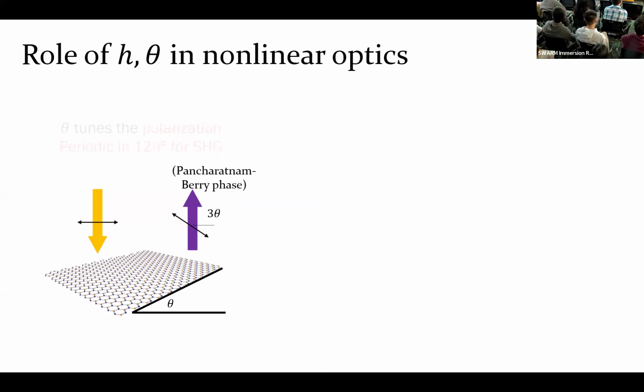So we're seeing that by changing the twist angle, or the angle of this one sheet of HBN, we're changing its polarization. Okay, and now if you think of a system that has two layers of HBN, and I'm rotating one layer with respect to the other one, then I'm changing the relative polarization between the second harmonic generation from the first layer, which has one polarization, and the second layer, which has a different polarization that is rotated by 3 times the twist angle, right? Okay.